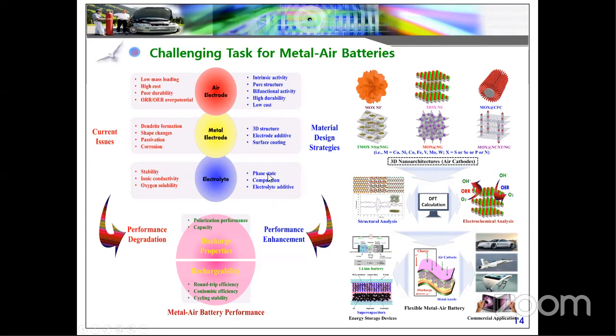We need to make a quasi-solid state, especially gel-based electrolytes, and that gel-based electrolyte needs some additives, so that it may increase the performance of metal-air batteries. So these are the performance degradations. To avoid this problem, we need to design materials that are highly stable and have more active sites. You can see different types of materials we have developed in our laboratory. After developing the materials, we need to optimize which material is best, because we need to optimize the ratio of the material.